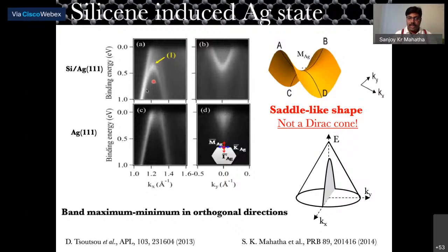In our case, we see parabolas in both cases, but along this direction we see a maximum and along this direction a minimum. And this can't be a cone. If it was a cone, we would expect a parabola like this. So what we claim is that this is a saddle-like band structure, like a horse saddle. It has a minimum along one direction, and the same point is a maximum along the orthogonal direction. So it's a saddle. This is not a Dirac cone.